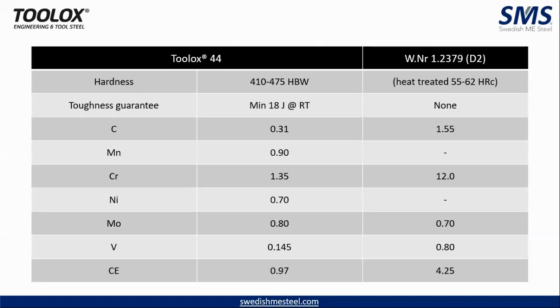Now we are taking the comparison between Toolox 44 and D2. The hardness is available at 410 to 475 HBW. D2 is available at 55 to 62 HRC after heat treatment. What you get is a toughness guarantee of 18 joules, which will not be available in normal cold working steels. It's a low alloy material, which helps in easy machining. At the same time, the carbon equivalent of the material is less than 1, which is much less than D2's value, which means Toolox 44 maintenance is easy. The thermal cutting and thermal welding that you can do on the material is very, very high.